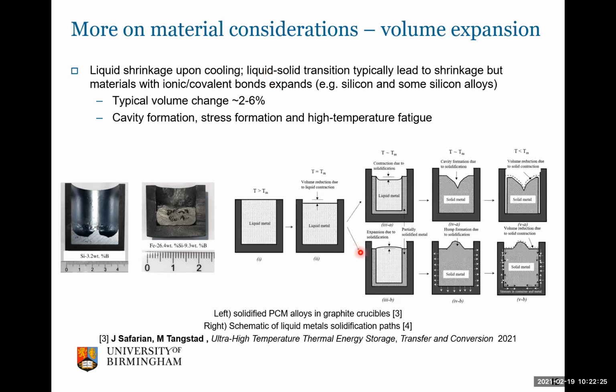And another key aspect to consider is the interaction between the PCM and the containment material. So we might have a behavior where the PCM does not stick to the wall of the containment. So the shrinkage is actually favorable because the PCM doesn't remain in contact with the containment, which facilitates the reduction of stresses that might be induced. Or in the opposite situation, we might have adhesion between the PCM and the containment, and especially if we also have expansion during solidification, that certainly leads to stresses in the containments, which are obviously challenging, especially at high temperature. So that's a clear aspect that needs to be considered during the development of a high temperature application of latent heat thermal storage.